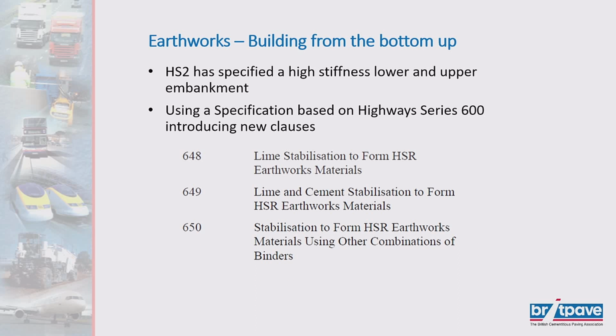and having spoken with some of the lead designers, they have actually put a very high specification on the earthworks. Because, as Al said, unless you start from the base up, anything you build, you wind up putting, as we would call it, a very nice skin on a rice pudding, which whatever you do to it, it's going to crack. So what they have done on HS2 is introduce 3 additional clauses based on Series 600, 648, 49 and 50, which is using the stabilisation of using lime or lime and cement to form the high-speed rail earthworks materials. And also 650 using other combinations of binders. If you can prove it works, it hasn't ruled out other binders. So it's not purely limited to straight lime and cement.